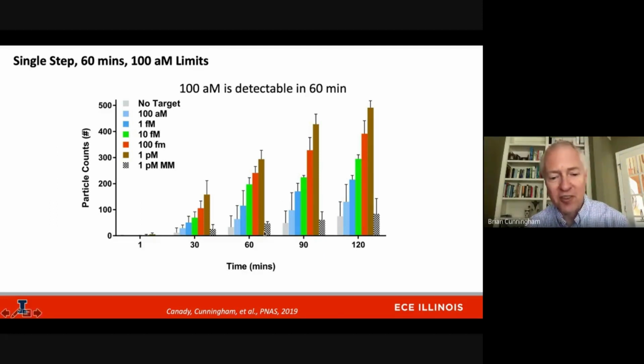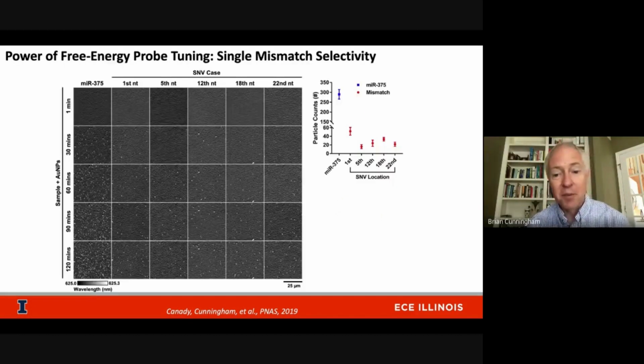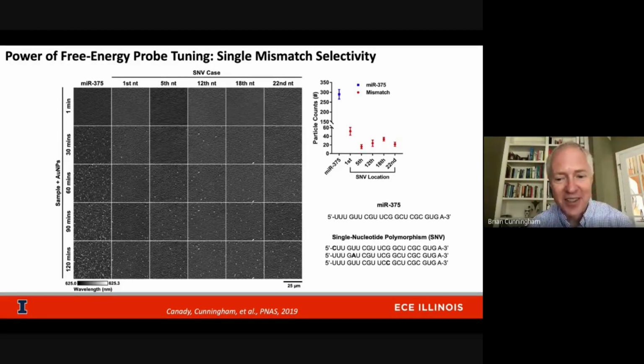And so this represents how selective the toehold probe method is. You can see how low the detection is from a non-target molecule differing from our target molecule by just 1 base, but at a 10,000 times higher concentration. We did some more things in our paper to characterize the selectivity and the placement of a mismatched molecule. So this just really shows how good the molecular biology is, so I won't spend too much time on this.